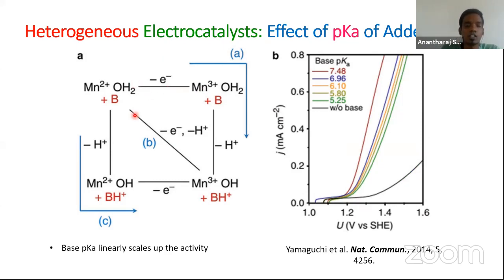In this case, I'm showing an example of MnO2 catalyzed neutral water oxidation. In the case of MnO2 catalyzed neutral water oxidation, what happens is that the very first step is forming Mn3+. This is the actual species which catalyzes OER, which has to be formed from MnO2. In MnO2, we know Mn is in tetravalent positive state, which has to undergo a disproportionation reaction where exactly half of the manganese is reduced to Mn2+ state, and half of the manganese is in Mn3+. So the Mn2+, which formed as a result of disproportionation, is going to be inactive unless it is converted back to Mn3+ species. Okay, so this can occur either this way or in a concerted pathway.